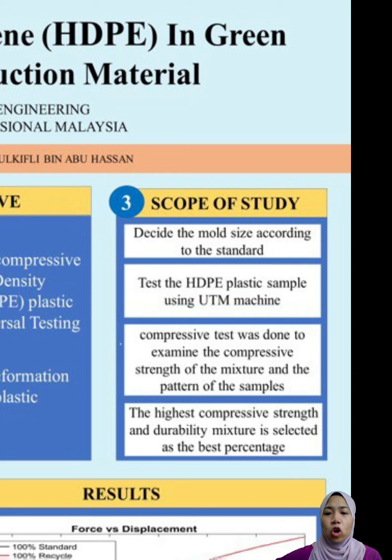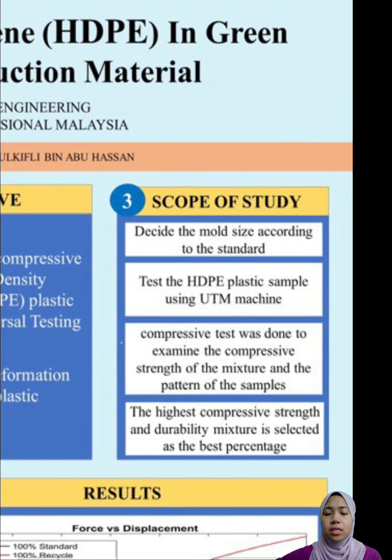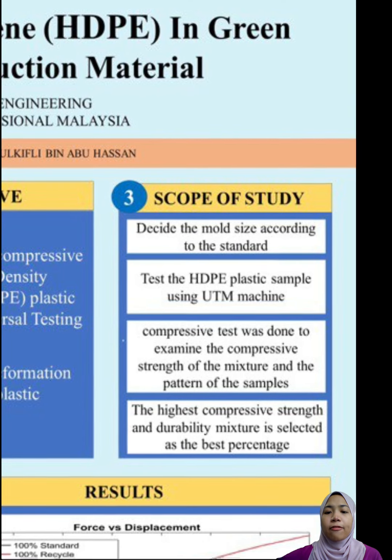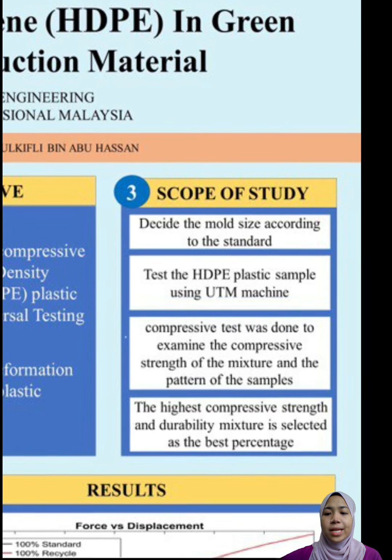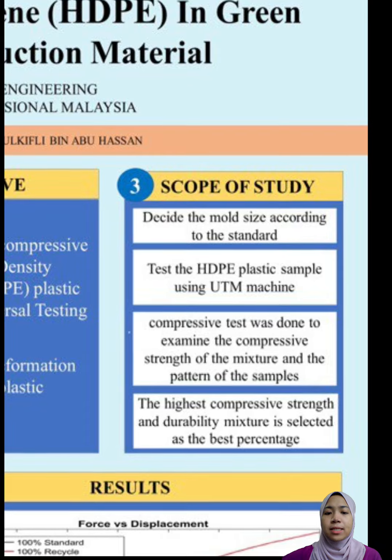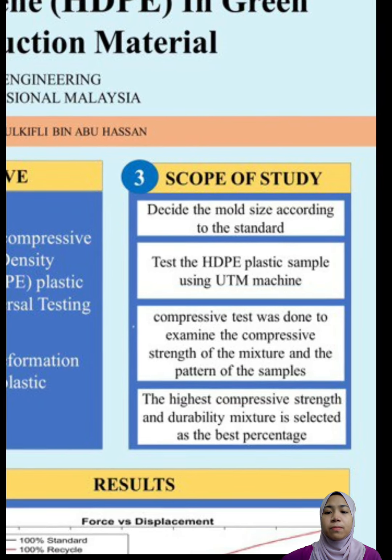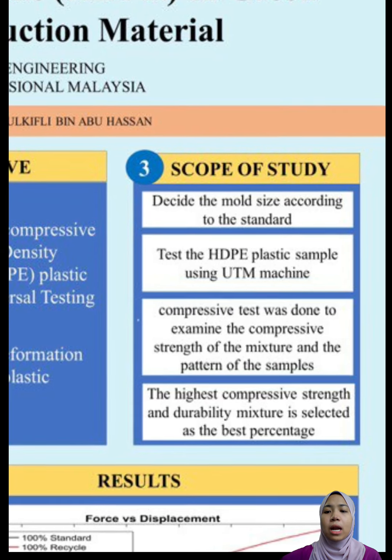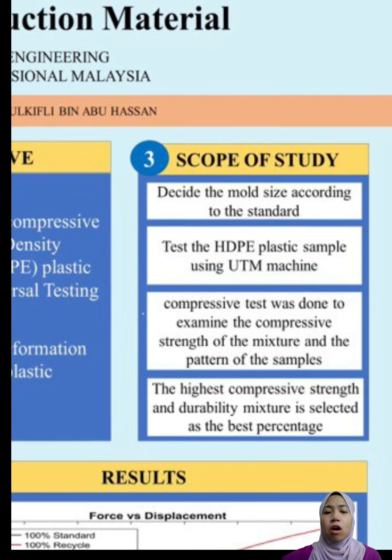After that, the compressive test was done to examine the compressive strength of the mixture. The compressive test result of each mixture was tabulated. Finally, the mixture with the highest compressive strength and durability is selected as the best percentage and compared to the deformation of each pattern.